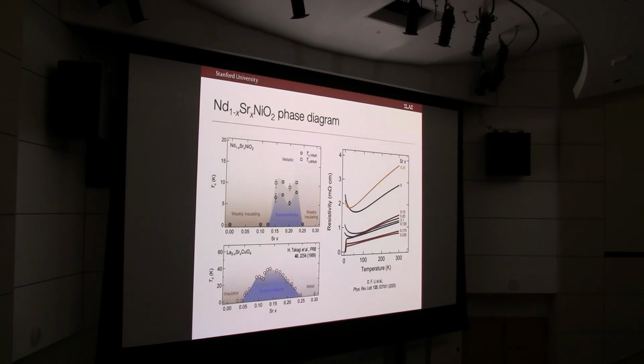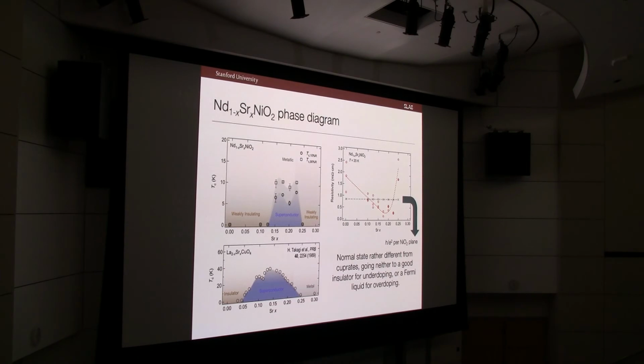the doping levels. An interesting distinction that we still don't fully understand is that whereas the cuprate has a good insulator on one side and a good metal on the other side, we are bounded by this weird weakly insulating upturn on both sides of the problem. One way you could at least parameterize that is the following. If we take the normal state resistivity just above superconductivity, we find that the scale of that resistivity as a function of doping has this kind of a minimum. And it's interesting that the occurrence of the superconducting ground state coincides where that resistivity dips below the scale set by a quantum resistance per nickel oxide plane. So we're just starting to get into the regime of coherent transport.